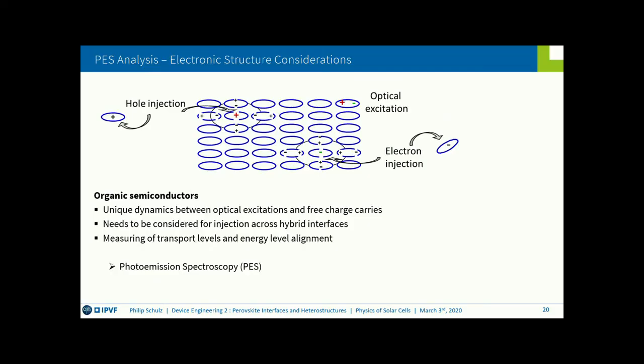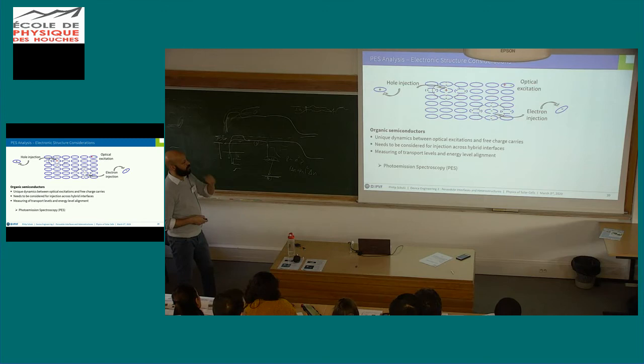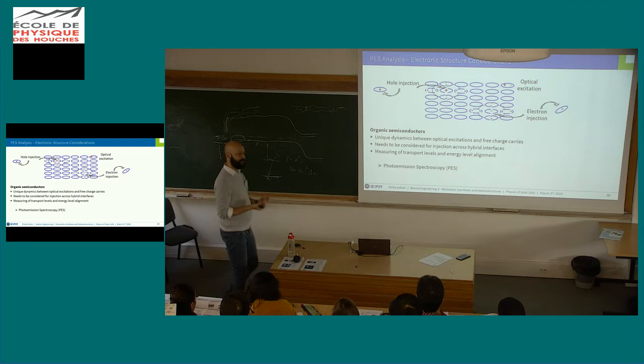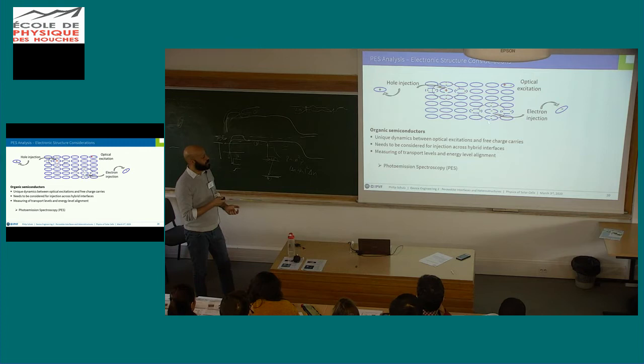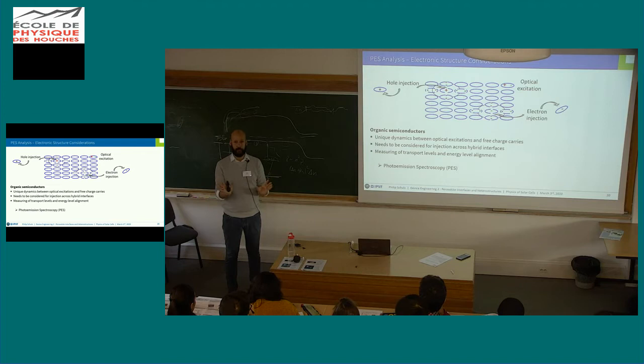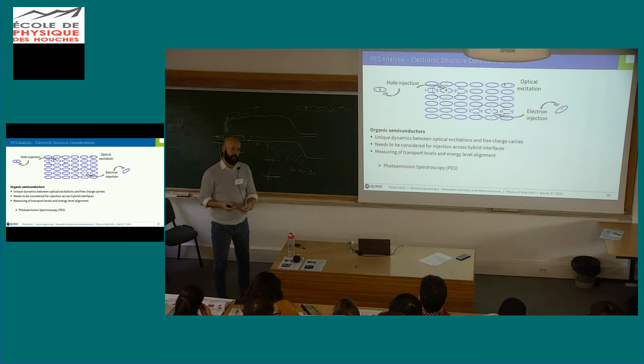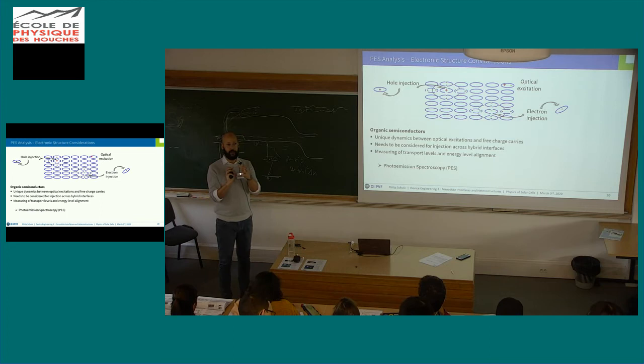So if we now move to this point here, I think this slide rather comes from an OLED slide, because we're talking about a carrier injection into the material and not extraction, but just imagine it to be the reverse of a photovoltaic cell. What you can see here is, however, that this one charge will polarize the molecules around. This can be a spatial distortion of the molecules. First of all, you have immediately electronic polarization. This is a process that you cannot avoid. But then, due to the molecular structure, you can, when you have this charge on the molecule, distort the molecule, so you really get a rearrangement of its structure. That leads to essentially a small structural defect that has often been treated as a polaron.